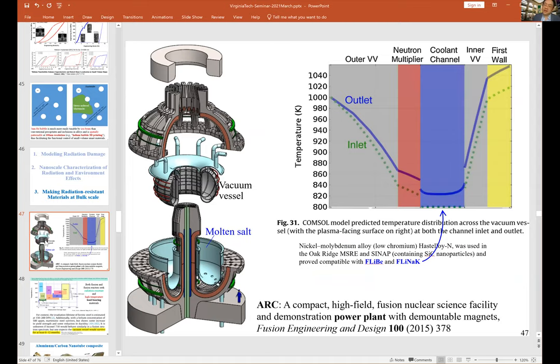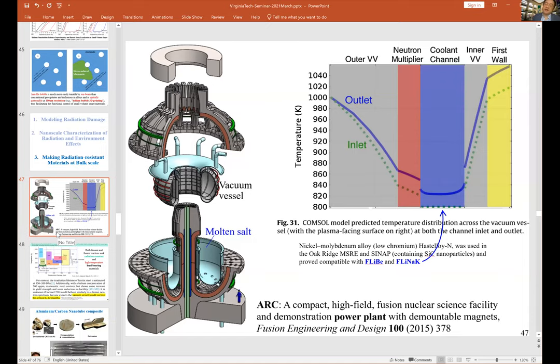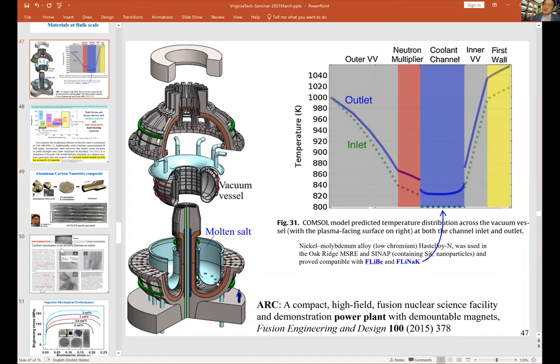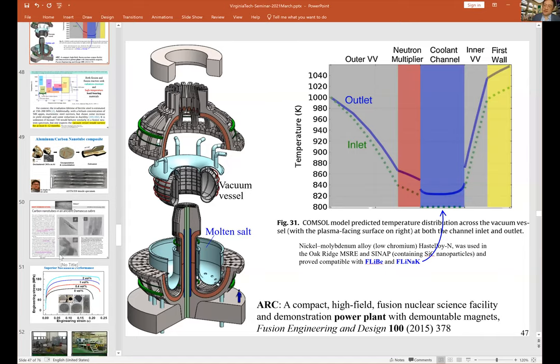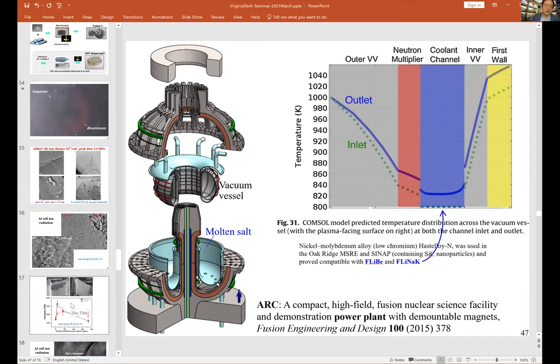Another way is if you can't do that, then you've got to have a lot of traps for helium. So computationally, we're working on what kind of nanostructure, what kind of interface can give you 0D or one dimensional traps. Those traps, even if the helium completely debonds those surfaces, do not give you a stress amplification factor of infinity. From elasticity, we know that if you have a cylindrical cavity, then you just get a stress amplification factor of 3. But you don't get infinity. So this is the idea behind this 1D nano dispersion. We think 1D is the best, because if you have the 0D nano dispersion like particles, then you don't get as good a creep resistance.